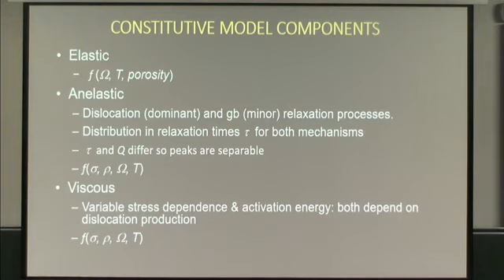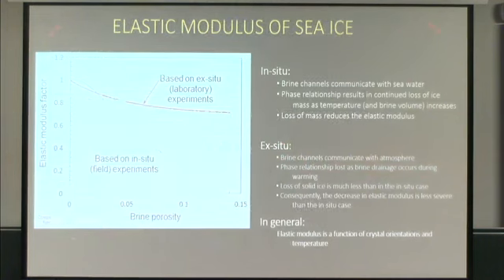One of the unanswered questions that I will answer is what's the difference between the elastic properties in the lab and in situ? Once we started running some higher temperature tests, we realized that there is actually quite a bit of difference. I'm not getting into the details of how the model calculates this, I'll just point that out. Most of our time will be spent on the anelastic component, which has two mechanisms, this dislocation mechanism and then the grain boundary sliding mechanism, both of which are quantified. I'll talk a bit about the viscous straining as well.